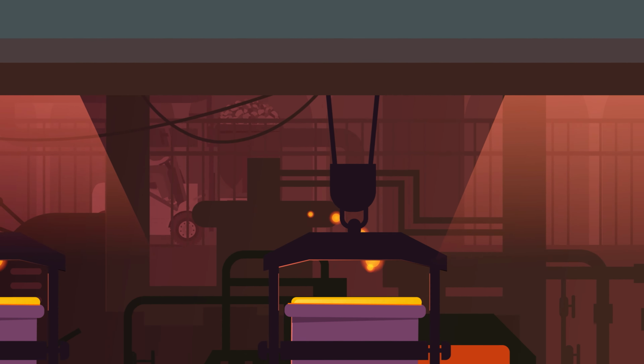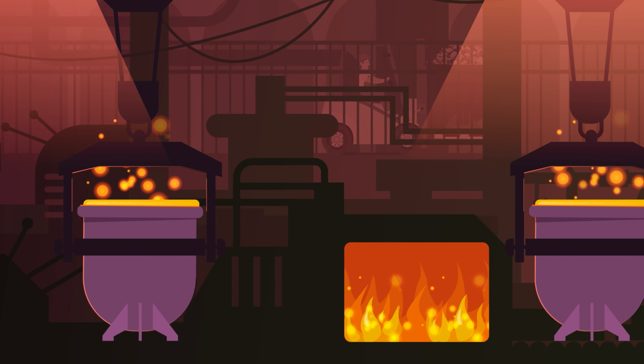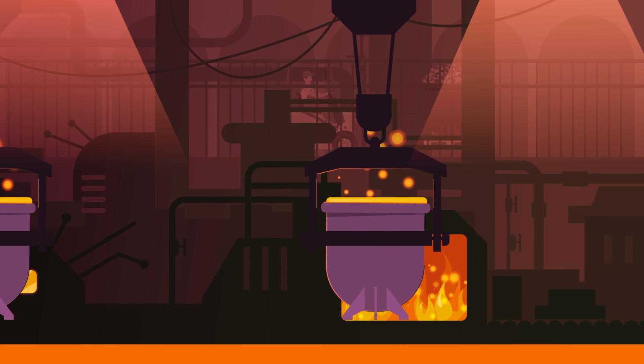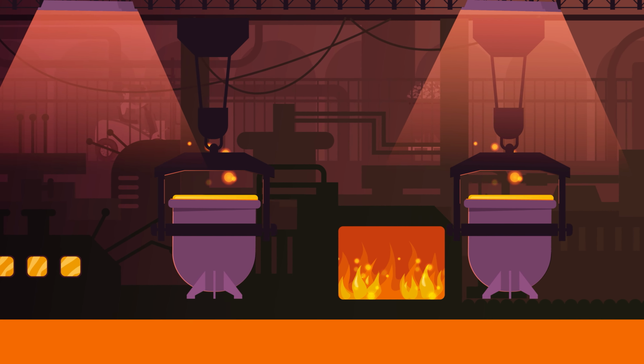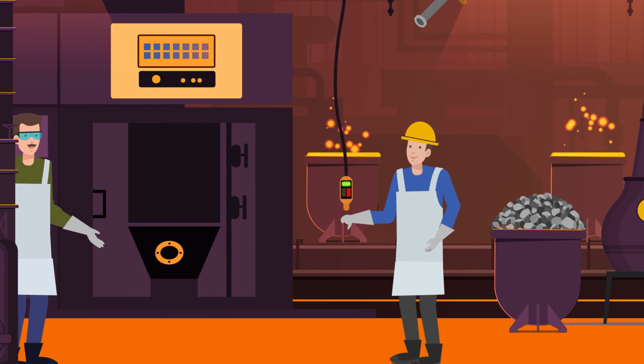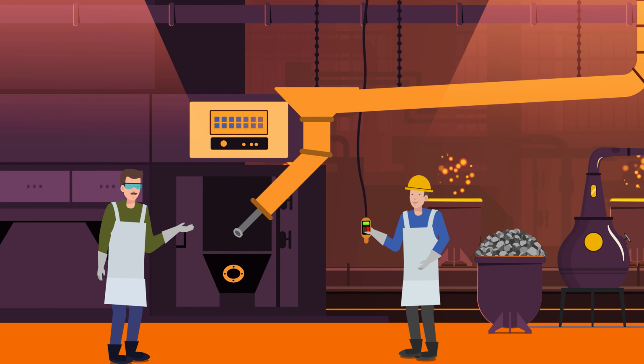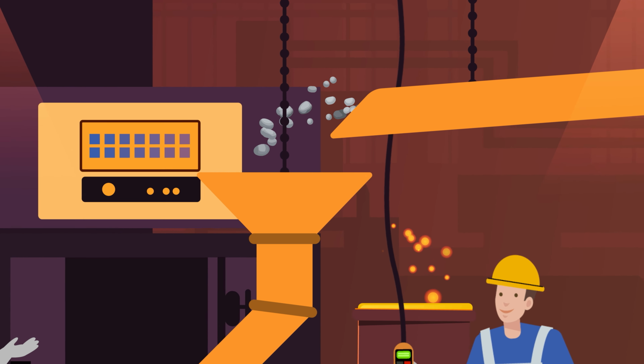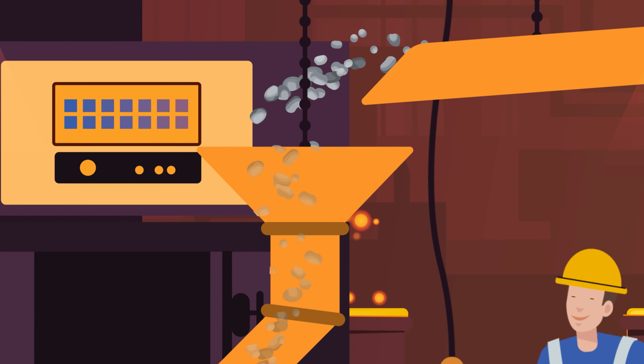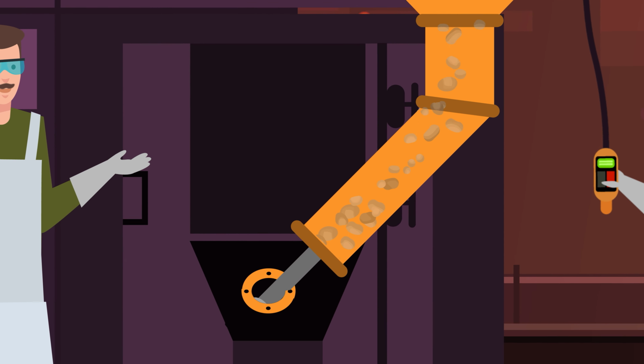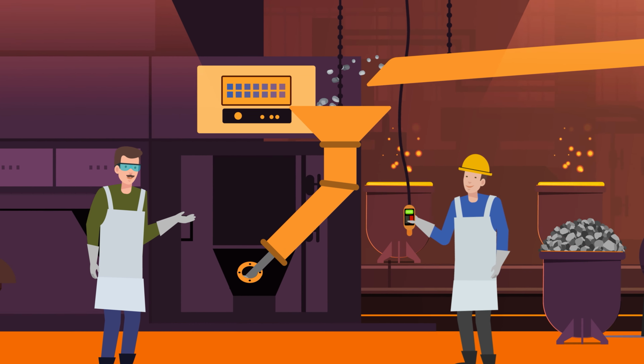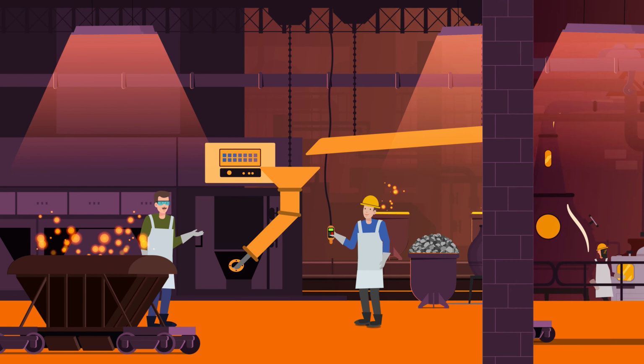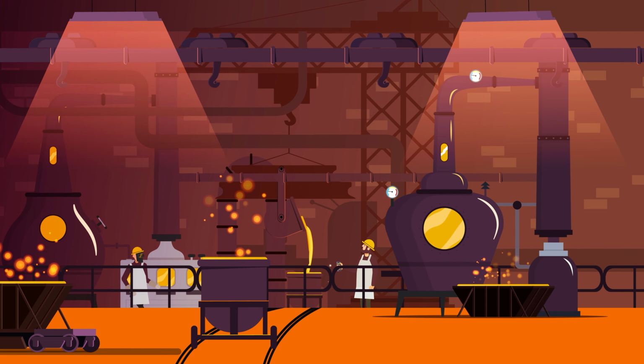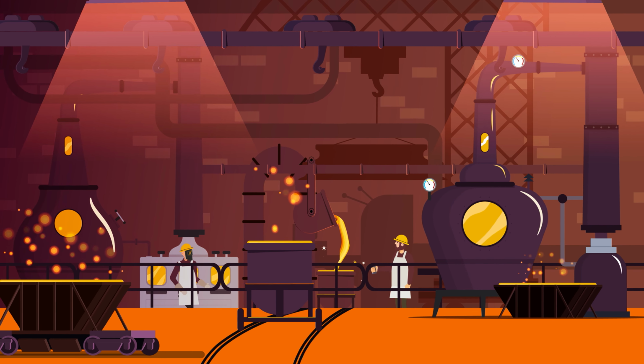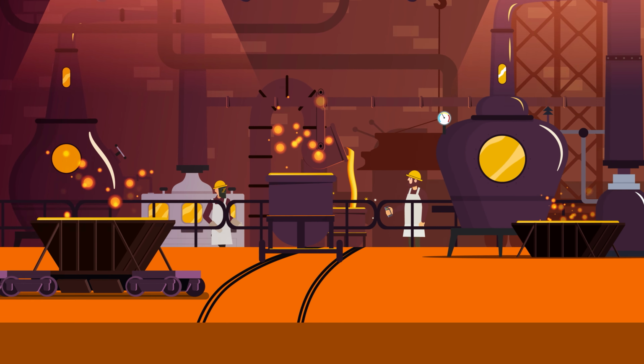After the initial smelting, the copper is further purified in converters, where air is injected into the molten metal to oxidize and eliminate remaining impurities. At this stage, electronic scrap rich in copper and precious metals is introduced. The electronic scrap is fed through a side chute, and air is injected into the melt to ensure efficient utilization and combustion. Processing electronic scrap in the copper smelter helps manage potentially harmful elements released when burned.